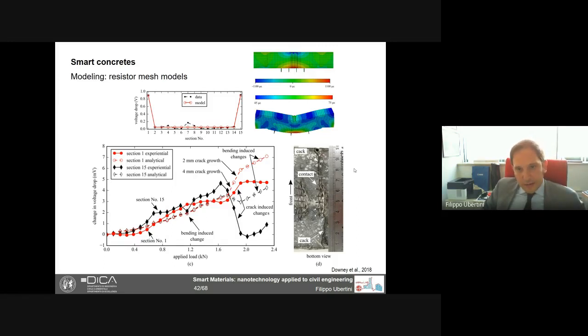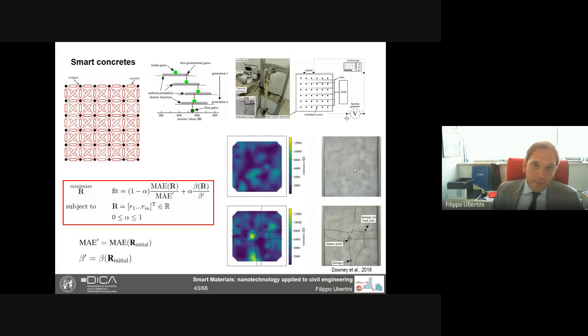So you see that there is not a perfect match, but for sure there is clearly the evidence that we get a consistent behavior between model and experiment. So when there is the crack, the two curves that before are overlapped just undergo a sort of bifurcation. One goes up and the other goes down, and the same is predicted by the model. So from here we can say that yes, we have something that we can use for detecting and locating a damage, and also to progressively track its severity.